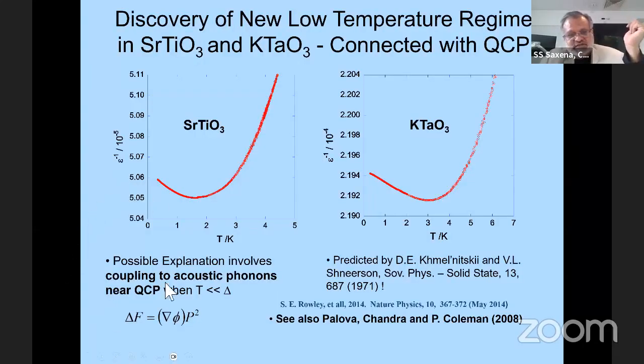And so if you look at the phenomena here and how we can explain it, so you have dielectric susceptibility, which of course is being reformulated because you're suppressing the long range order. Here it's been done naturally. And then you have the acoustic phonon near quantum critical point, which is possibly coupled to it to give it a local minima. This is based on the Khmel'nitskii paper from 71, in fact, and it was an earlier one even.